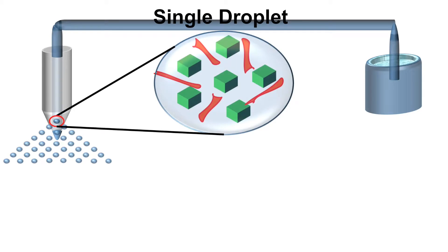In order to have that disordered structure, I use an instrument called a spray dryer. For that, I prepare a mixture of the drug — let's say ibuprofen — and a polymer in an aqueous solution. Then I spray it into thousands of small droplets. If you look closer at one of these small droplets, you see a mixture of crystals of ibuprofen beside polymers, shown here in red, in a bed of liquid — let's say water.